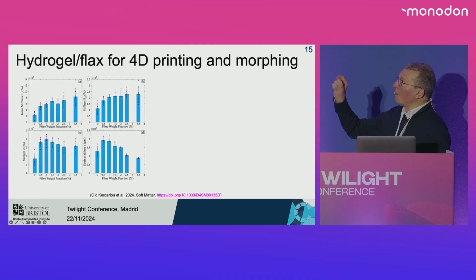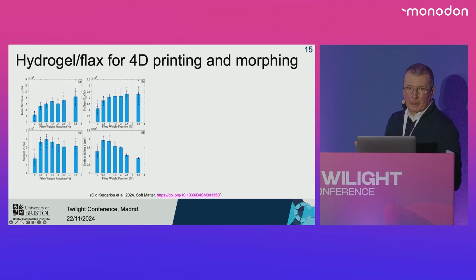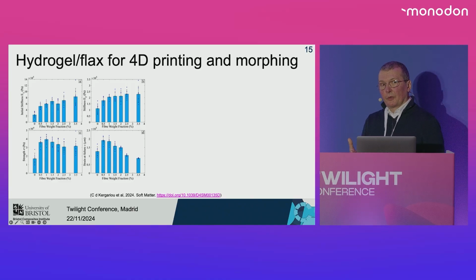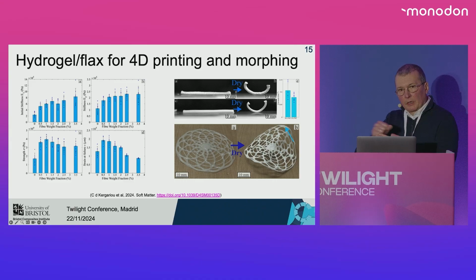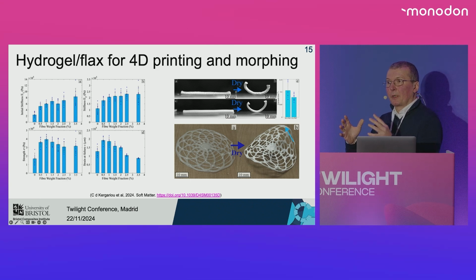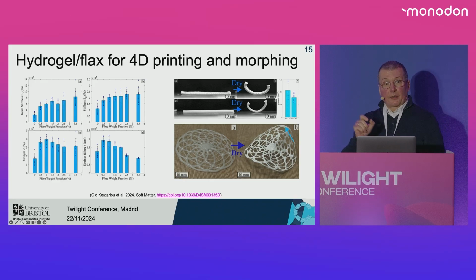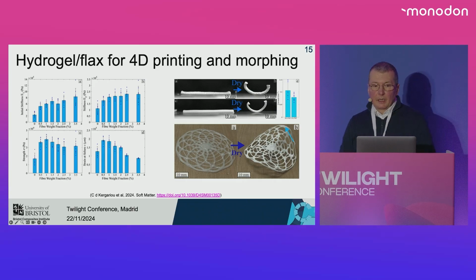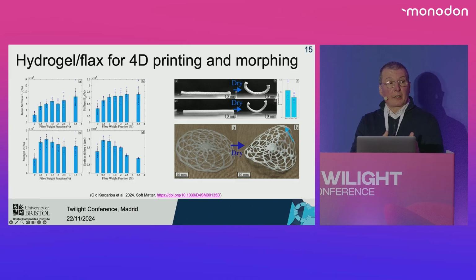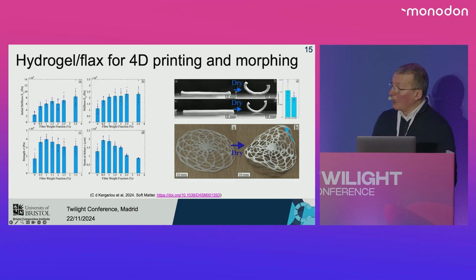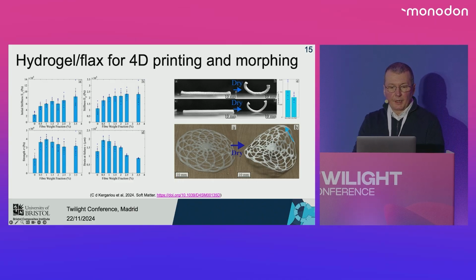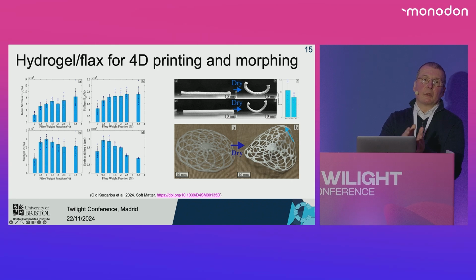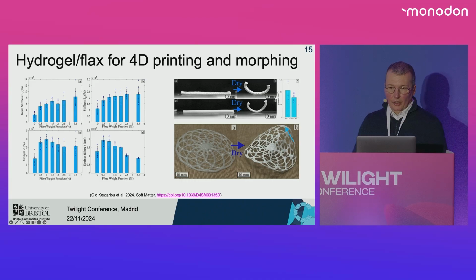And also, if you look beyond the 1% of weight fraction in terms of stiffness, there isn't really a big increase. So diluted dispersions actually already work quite effectively, not only in terms of reinforcement properties, but also to provide this type of shape morphing properties when we have changes of relative humidity in the surrounding environment. In this case, it's not only the flax that acts with the hygroscopic strain to provide the overall shape morphing. It is also the hydrogel that contributes to the hygroscopic deformation. And you can see over there is an example. We printed a rosette in wet state, and when it's put in dry state, for us typically 20–25% of relative humidity, we have this change of shape.